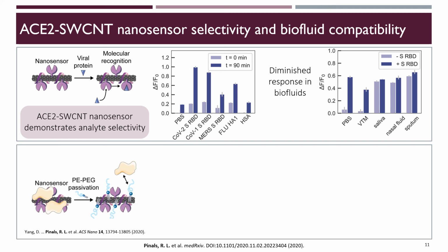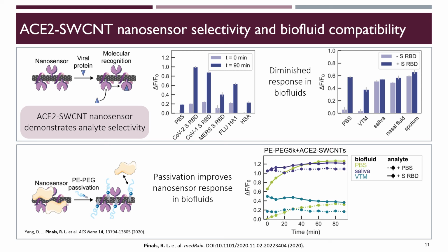To mitigate formation of this unfavorable unintentional protein corona, we employed a passivation strategy with phospholipids that are attached to the hydrophilic polymer polyethylene glycol, or PEPEG, as previously demonstrated in our lab. This passivation enables some retention of nanosensor function in saliva, yet poses a challenge that we are pursuing with ongoing optimization.